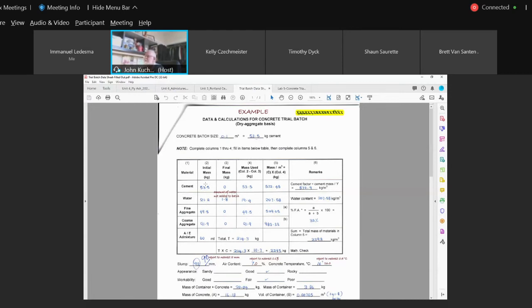Now, so you weigh these out, and then you dump them into the mixer. But when you dump things in the mixer, don't ever dump all your water. This 21.2 kgs of water is also to account for how much is going to be absorbed, okay? So you would use your adjusted water added to your total. This is your total water. Now this column here says final mass. Well, if you're going to use all your aggregates and all your water, these would all be zero.